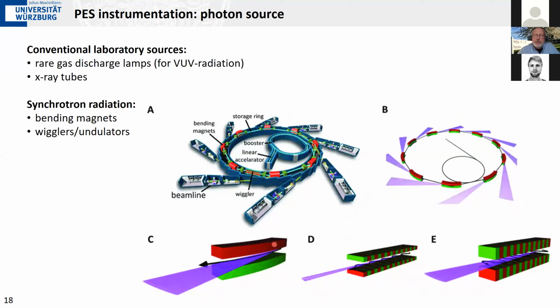For example, if you do not use a homogeneous magnetic field here, but an alternating field, by putting here magnetic pole pairs in reverse and alternating orientation, you can wiggle the electron beam here. I don't know if you can see this very well. And that produces a much finer focused and much more intense beam. In fact, if you apply very high magnetic fields here, and you adjust the field strength by the distance of these pole pair shoes, that's the so-called gap, you get an undulator where this light is coherently excited. And these are also the structures used here in synchrotron facilities, but they are also used in particular in the new free electron laser facilities that we have at some places in the world.